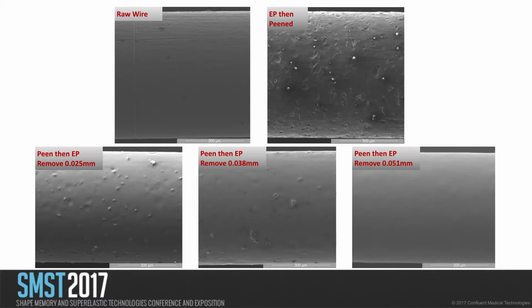Up here in the upper left-hand corner, you see an image of the raw wire. Moving over to the upper right, you see an image of wire that had been EP'd and then peened. These white high contrast areas are actual peening media that is still contaminating the surface of the part. Moving down to the lower left-hand corner, you see wire that has been peened and then EP'd to remove 0.025 millimeters. You still see those areas of high contrast, and when analyzed through EDAX, that was concluded to be peening media. So those wires were still considered to be non-biocompatible.